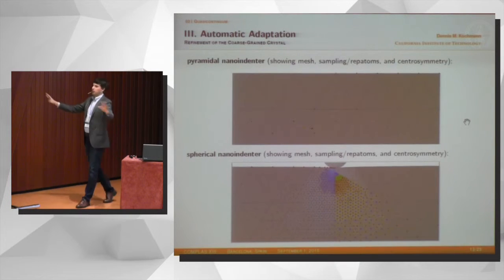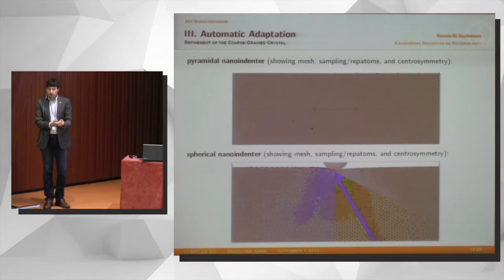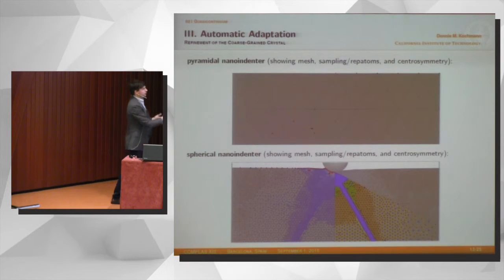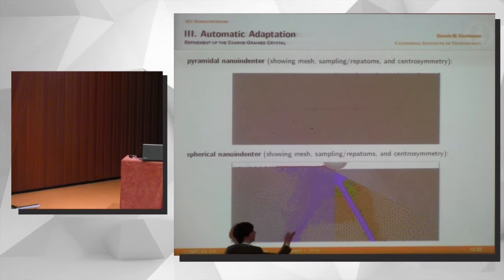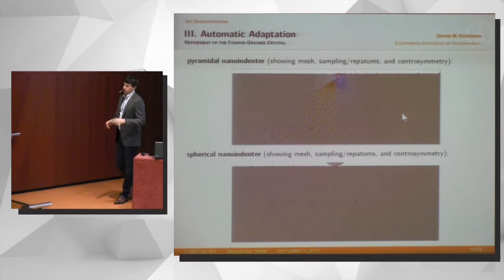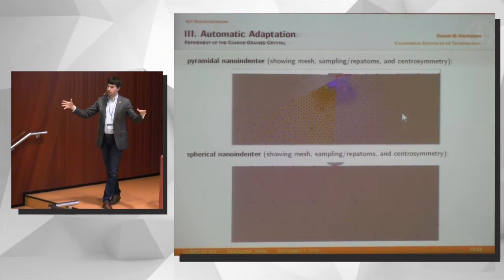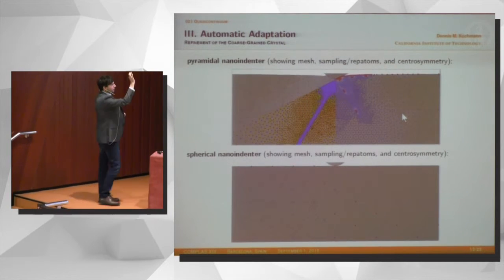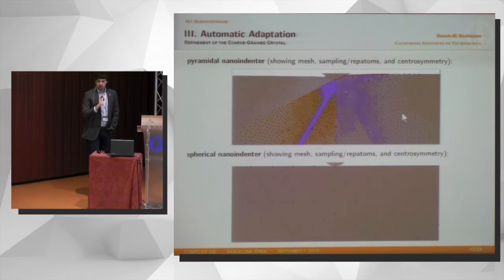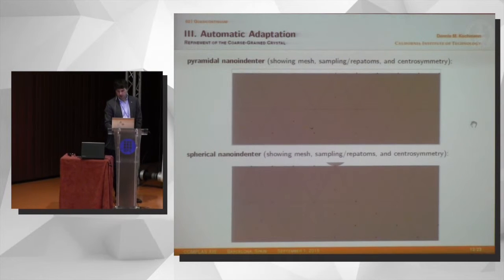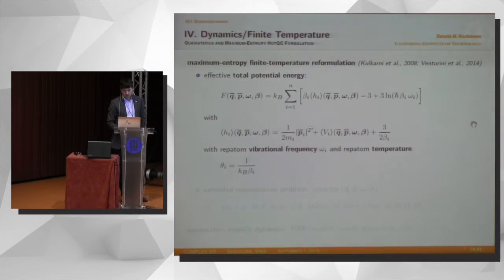And so you can start with the most coarse mesh you want. The minute that you localize, the minute that you create dislocations that are running through the crystal, the mesh automatically refines, it recovers those dislocations, and you ensure that while you're running this with the efficiency of a continuum scale, you can still track down each and every dislocation, and each and every dislocation is modeled atomistically. So we don't have to introduce any continuum representation of those defects.